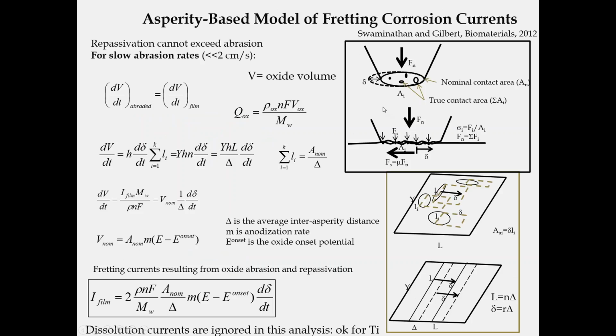Additionally, we've taken it a step further, and Vishwa Swaminathan and I, back in 2012, published a paper in Biomaterials that took a pin-on-disc geometry and thought about the asperity-like contact that goes on, and essentially made the assumption that whatever abraded area there is per unit time, you're going to have film forming currents or a volume of film reform that is equal to that. In other words, as the volume abrades, you are reforming it very rapidly right behind there.